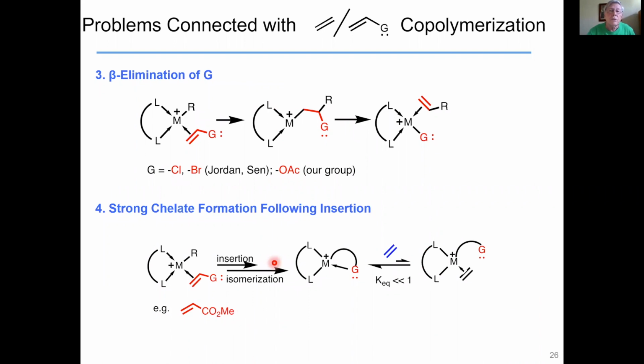There's also an issue of beta elimination. If you do insert, and the functional group ends up beta to the metal center, you can get a beta X or beta G, as I show here, elimination to kill your catalyst. Rich Jordan and Ayusman Sen demonstrated this for vinyl chloride and vinyl bromide. Our group showed the same problem with vinyl acetate.